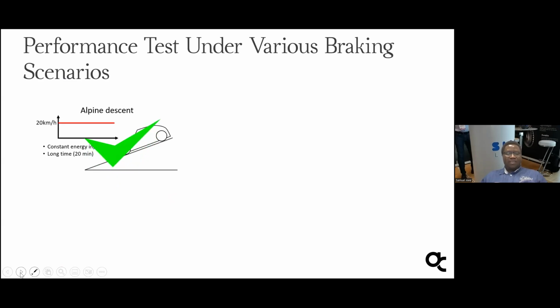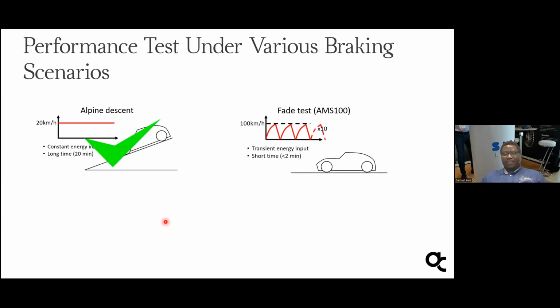And the next is the fade test, which is also called AMS 100. This is to see how the friction couple could cope under different testing conditions, extreme driving conditions in a very short time, less than 2 minutes. So you drive from 100 km/h, then to 0. You brake at maximum to 0. So at 10 different occasions.